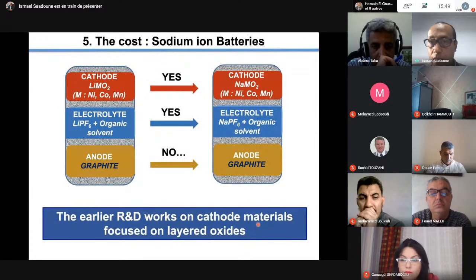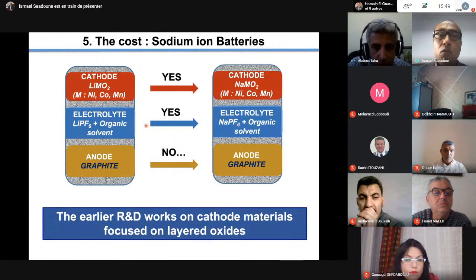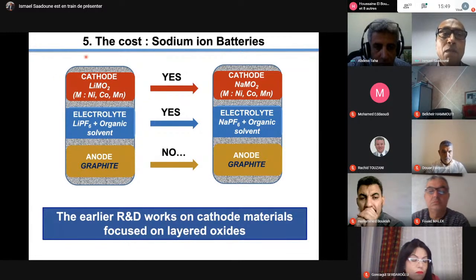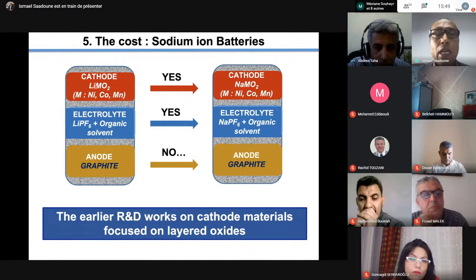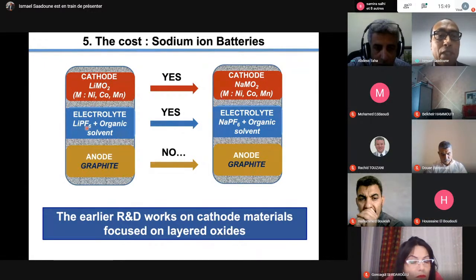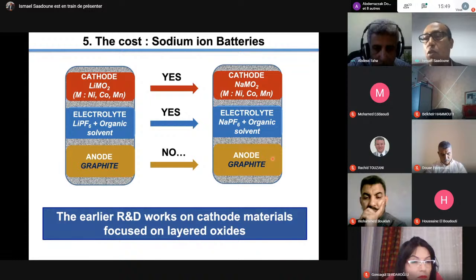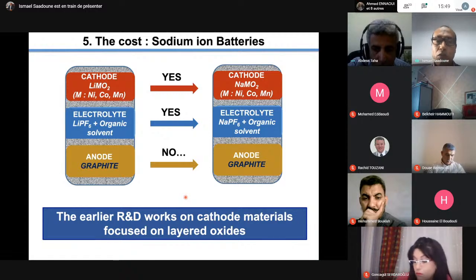The first reflex, the first thinking, is to translate what we found for lithium since 1992 to sodium. So we replace the cathode lithium metal oxide with sodium metal oxide. It works. We change the electrolyte from LiPF6 to sodium PF6. It works. But the problem was in the anode - graphite doesn't work for sodium in batteries. So we should think about what kind of anode to use in this new concept of sodium-ion battery.